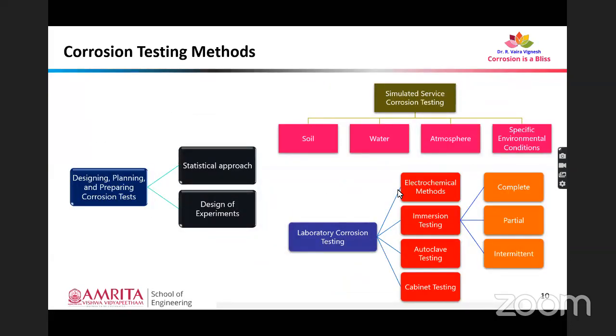So that involves designing, planning, and preparation of corrosion tests for the specimens. That includes statistical approach and design of experimental approach. Generally speaking, corrosion testing methods rely on simulated service corrosion testing environments or laboratory corrosion testing environments. In simulated service corrosion testing, we just place the specimen in the respective environment, and then we evaluate the corrosion characteristics of the material. But in laboratory corrosion testing, we do it by mimicking the environment.